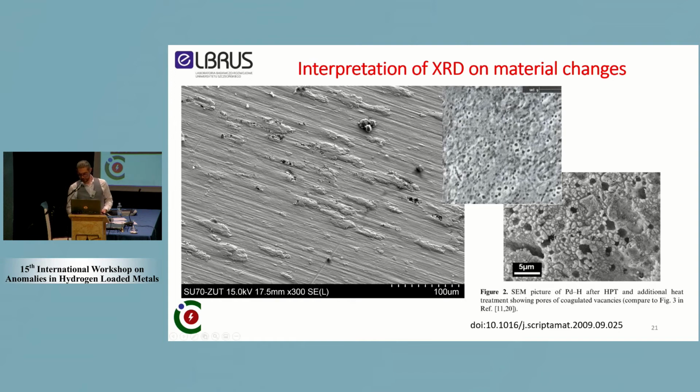The reading I have, as now quite well documented in the bibliography of the superabundant vacancy, is a clustering of the vacancies, and then a migration of those clusters of vacancies to the surface of the material.